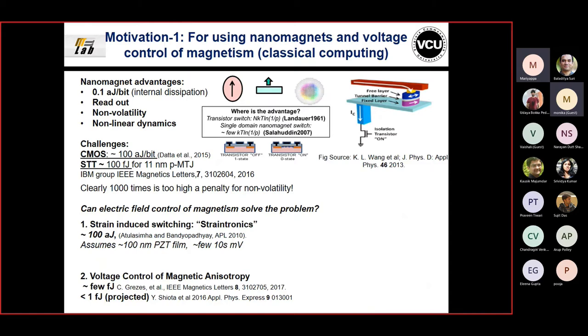A little historic context: if you look at the work of Landauer and others, why they argue for nanomagnets - at that time for a transistor, you need N electrons (when N equals a million) going into the channel and out to go from on to off state. If P is the error probability, the energy would be N·kT·log(1/P_error). Whereas in a magnet, you could have 10^5 or 10^6 spins, but they're all exchange coupled and switch in a correlated fashion. So it's not exactly kT·log(1/P) - it's a few degrees of freedom. This was inherently the advantage.